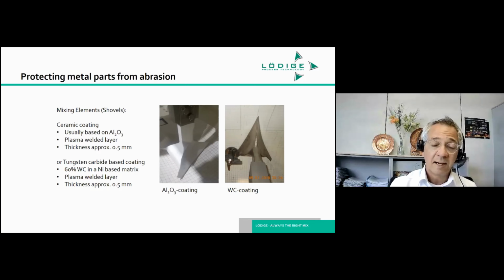And the reason it's a drawback is that you can never prevent foreign bodies like nuts, bolts, whatever, large objects, from coming into the mixer together with the raw material. And if this happens and the mixing action is there, and these foreign objects hit the mixing tool, then if the coating is brittle, you get chances that the coating will split off and you will see the underlying metal. Again, this will provide a location for contamination.